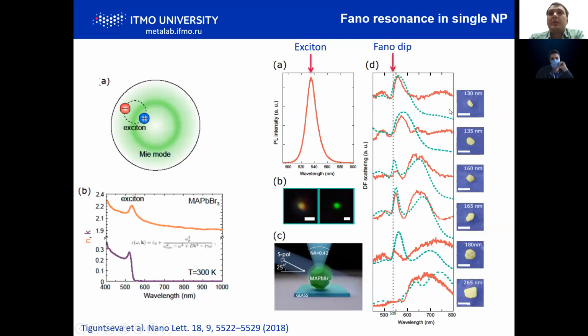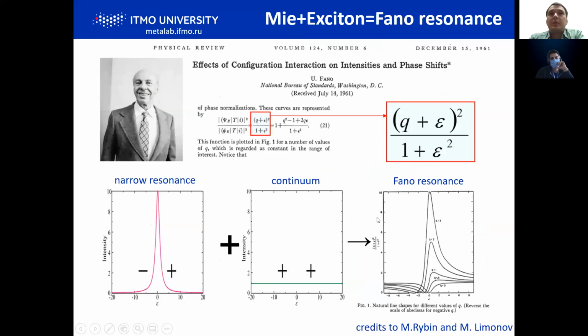And we see that at some sizes, more than 100 nanometers, we have some Mie-like behavior. So we have strong scattering at some spectral ranges. And we always see a dip, some minimum around one wavelength, which corresponds to the position of the exciton of the bulk material. And this dip is due to Fano resonance between a relatively broad Mie resonance and a narrow excitonic resonance. So in this case, we couple these two types of modes, and such a minimum can be observed in the scattering spectrum.